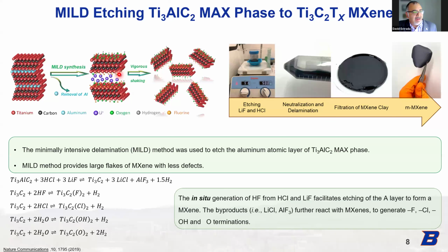We learned from Yuri's team how to synthesize these, and we've been applying the in situ HF synthesis method, where we do an in situ reaction to generate HF by mixing acid and fluoride, and this facilitates the etching of the aluminum layer from the Ti3AlC2 MAX phase. We do that etching just on a hot plate over time. We neutralize that, wash it multiple steps, and then we pour the MXene clay, let it dry, and then we get these MXene papers, which we can then formulate into our co-solvent systems for the platform of choice.